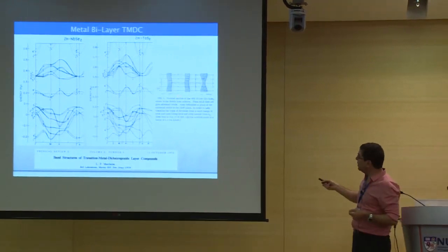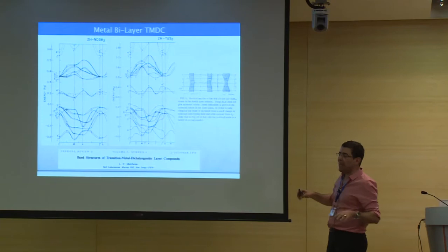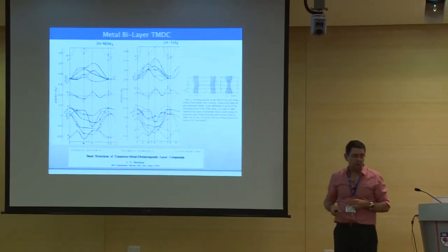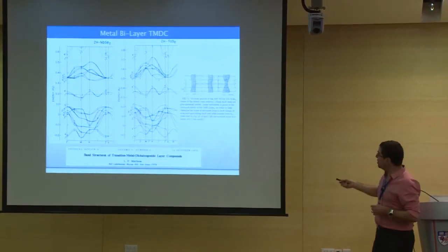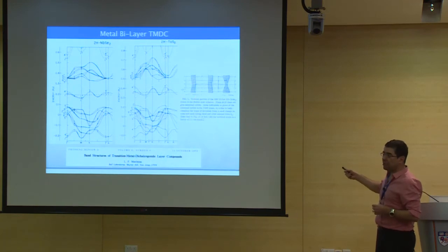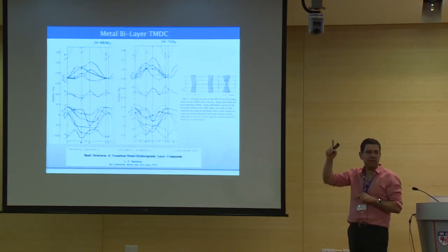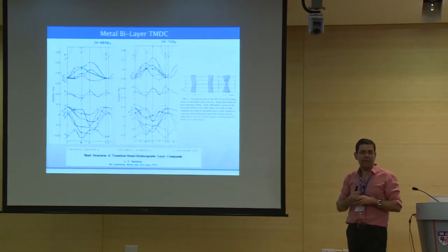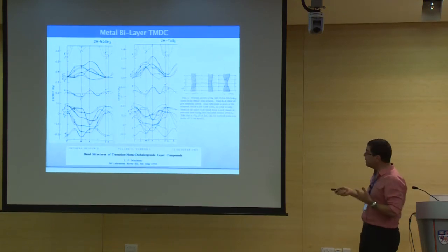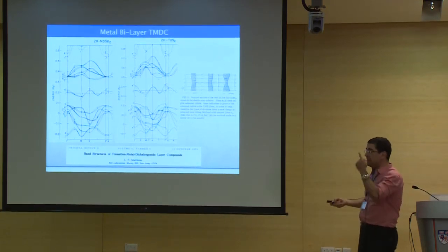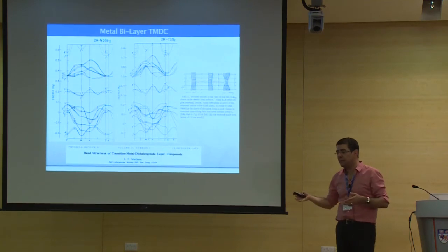And if you look at the dispersion out of these planes, and this goes back to what Francois was saying before, these are very, very flat. So there is almost no dispersion in the bands in the direction perpendicular to the plane of these materials. This means that the conduction along the z-axis is much, much worse than the conduction in the plane.